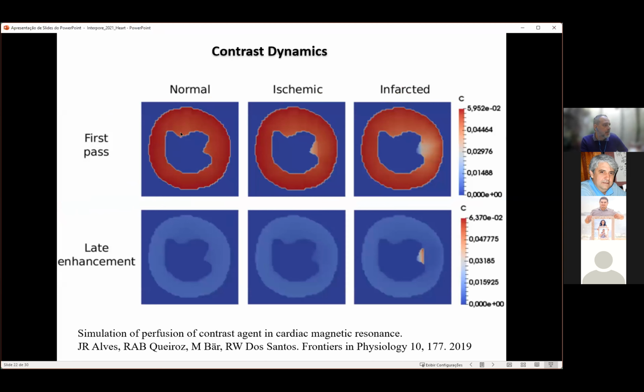So this is the first pass. The contrast in the normal just highlights everything. And after a while, you do again the magnetic resonance, and there's no contrast anymore. So here's the contrast when you have an ischemic situation. On the first pass, you see a shadow here. This will be like a black shadow. There's not enough contrast here because our coronary obstruction was here. But fortunately, this was not so bad. So the tissues didn't die, the cells didn't die. So if you wait and do again the exam, MRI, there's no gadolinium-based contrast trapped here.